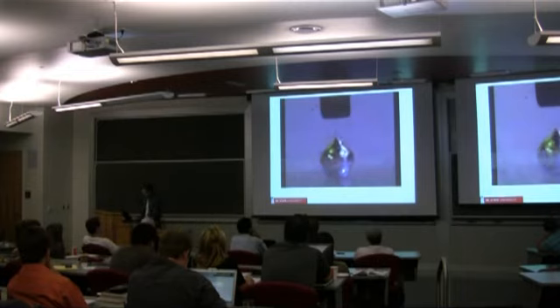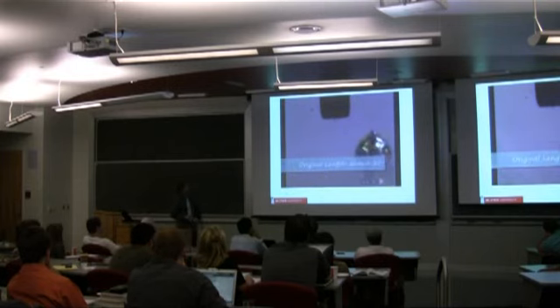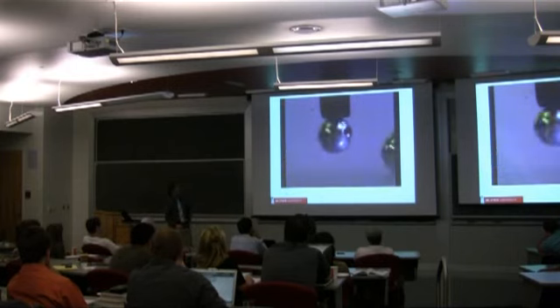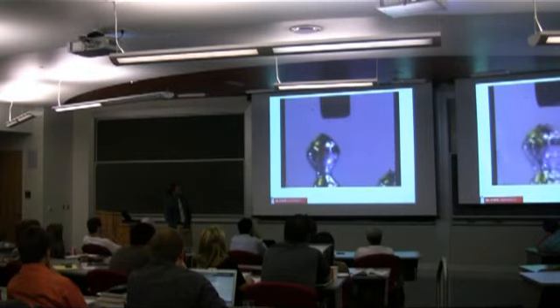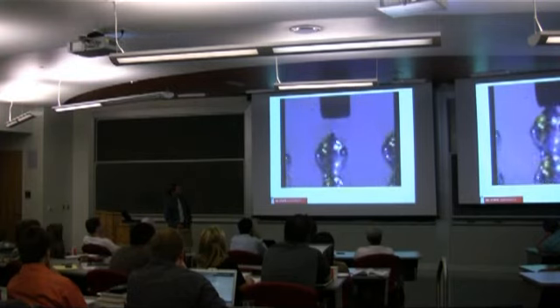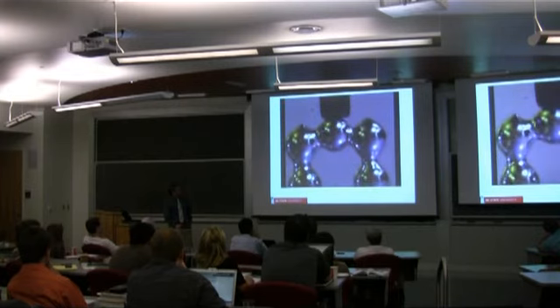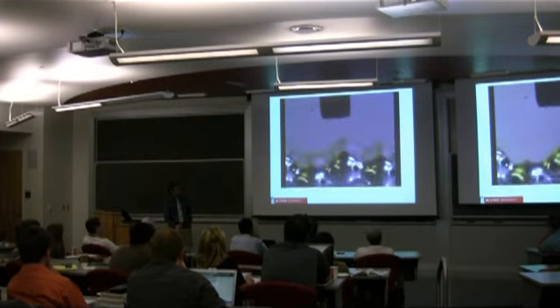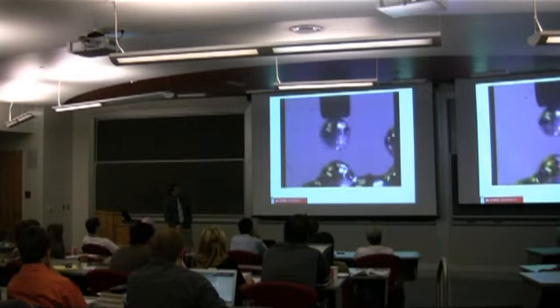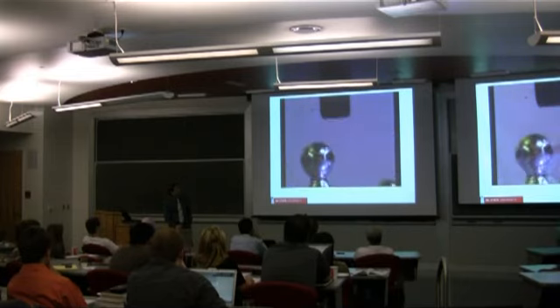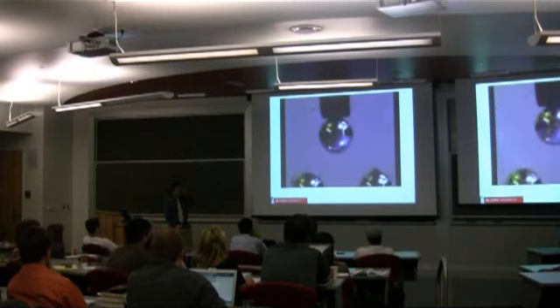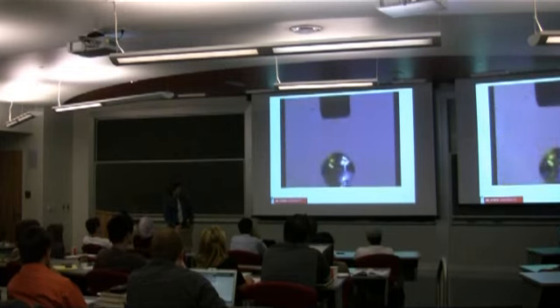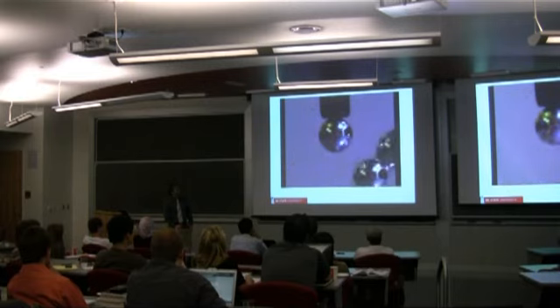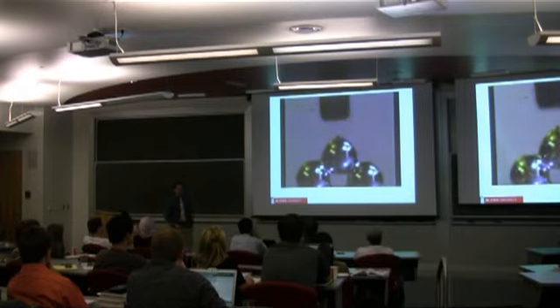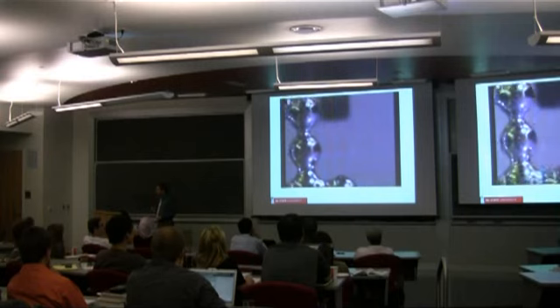And a really amazing undergrad built this tool in my lab where you can take droplets and dispense them. That's not all that interesting, but now you see that you can stack them. And this is coming out of the plane. And these things hold their shape. So this gives you a sense of how fast the oxide forms. It basically forms immediately. But it's thin enough that the structures can merge together. And you can start patterning these things, sort of direct writing metallic structures out of plane. Usually I get some oohs and ahs. You guys are tough. Okay, I'll try better.